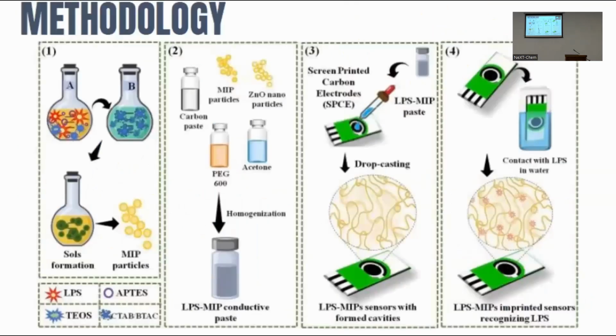To develop such a sensing tool, a protocol methodology with 4 steps is presented here. The first step refers to the preparation of 2 series of MIP particles with LPS molecule by sol-gel technique. Herein, 2 solutions were mixed, one containing the precursor gel solution, meaning the target molecule LPS, the monomer tetraethoxysilane and the aminopropyl triethoxysilane, and the cetyltrimethylammonium bromide or benzyltrimethylammonium chloride as surfactants dissolved in ethanol, and the catalytic medium based on ammonium hydroxide water mixture.